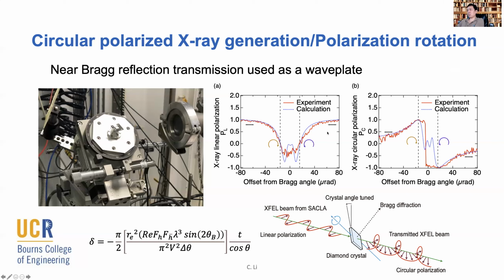You can tell that even with our best trial, the experiment only agrees partially well with the calculation, and we definitely lose a lot of fine resolution in terms of control of the polarization. But that's the hope. We hope we achieve a fully circularized beam near here, a right-hand circular polarized beam here, and a left-hand polarized beam here. In principle, we should be able to achieve a rotation of the linear polarization too, but we haven't tried that yet. So once we got this, we thought, let's play with the circularly polarized X-ray and see what we can do when we do inelastic X-ray scattering with it.